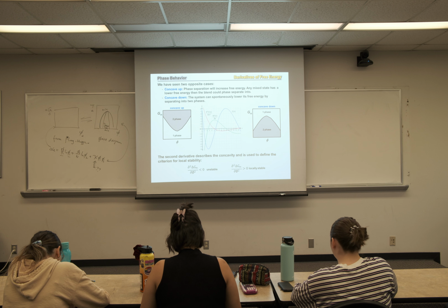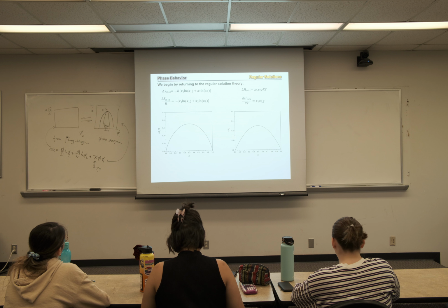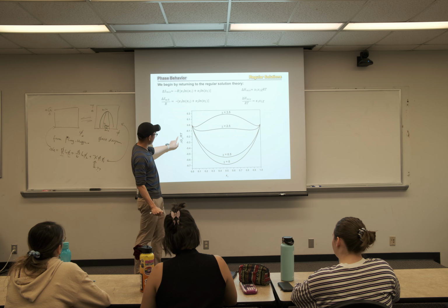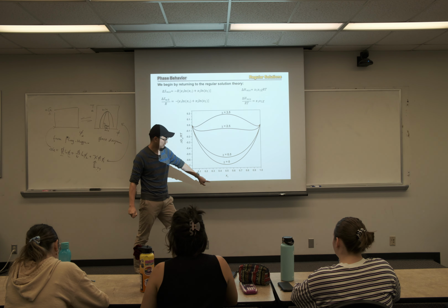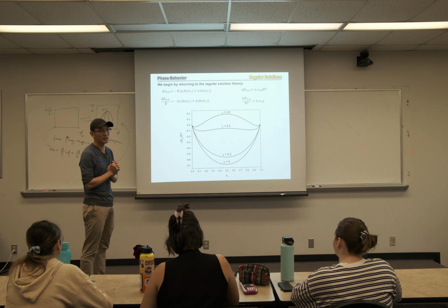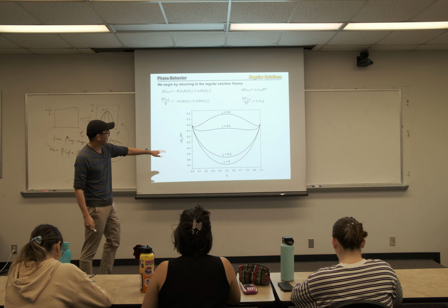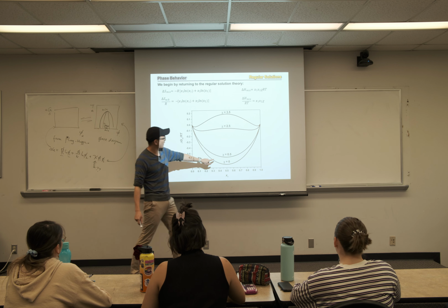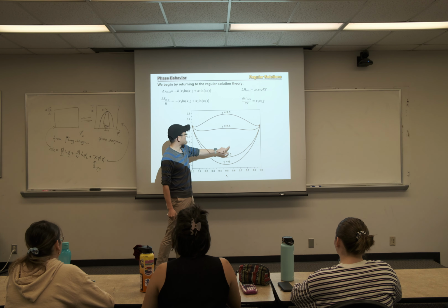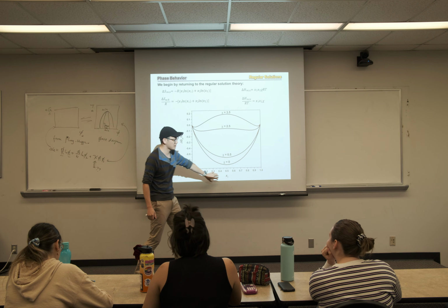So in the last lecture, we explained two important concepts. First is how to construct a delta G divided by RT versus X1 curve. X1 and phi 1 have a similar scope. It depends on whether you're mixing solvents or mixing polymer and solvents, okay? We talked a little about that. If I give you a chi value, if it's known for the polymer, chi equals 0, 0.5, or 2.5 or something, you can easily construct this delta G versus X curve.